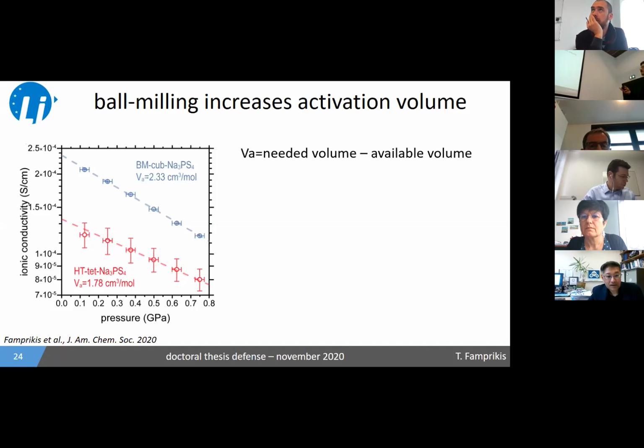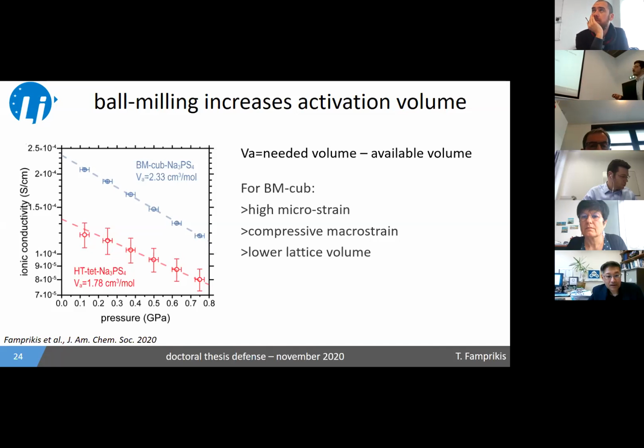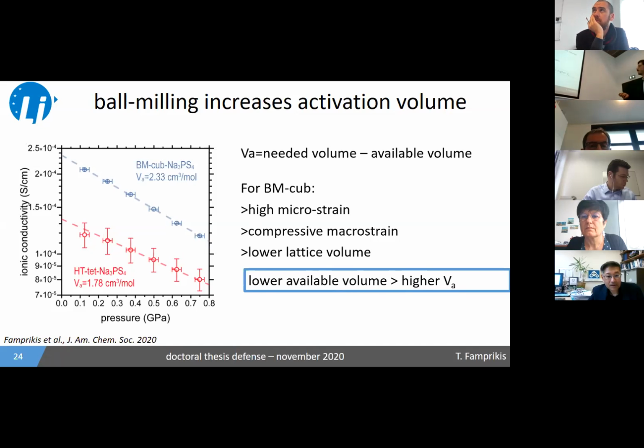In order to understand this difference, you can conceive of the activation volume as the difference between the needed volume for ion migration and the volume that is already available in the crystal structure. So if I remind you that for the ball mill sample, we have high microstrain and a compressive macrostrain, so a lower lattice volume, lower available volume for conduction, you can understand that this can be directly linked to that. So lower available volume leads to a higher activation volume. Basically, the local expansion of the lattice will need to be higher for ions to move in the ball mill sample.